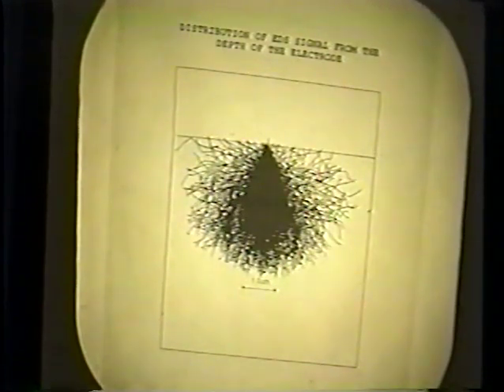Electron from the outer core will jump down to fill that gap, and that will produce X-ray emission, which is usually between 0 and 10 kiloelectron volts for different elements. Now, this X-ray, which is detected on the surface, can travel as long as a couple of micrometers. It's no problem, even more.